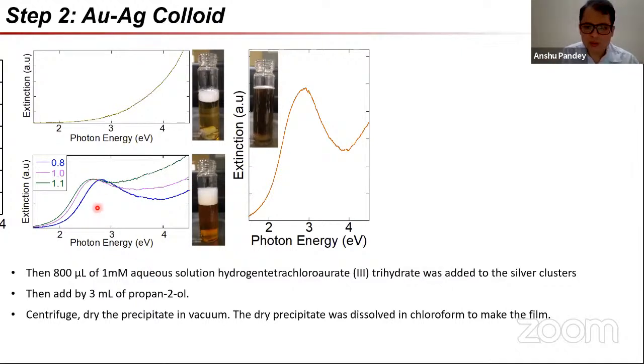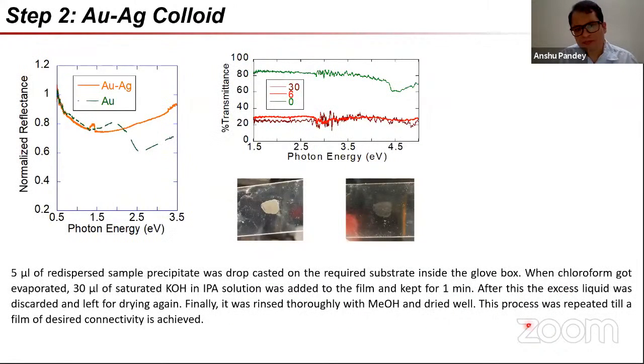Once we get to around a 2.5 eV, 2.6 eV window, we then stop this reaction right there. And at that stage, this 3 ml of propanol is added, or we use some other reagents to destabilize. We've tried other things like acetone, etc. So at that point, this aggregation does start, and this reaction mixture darkens quite a bit. This is then centrifuged, the precipitate is dried, and we redissolve it in chloroform to make the film.